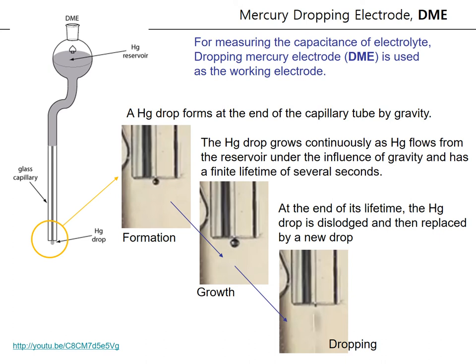Right now, we recognize the relationship between the surface tension and capacitance. So from the surface tension data, we could calculate the capacitance as a function of potential. For measuring the surface tension, usually we use the dropping mercury electrode as the working electrode. So finally, we could obtain the capacitance value of the electrolyte.